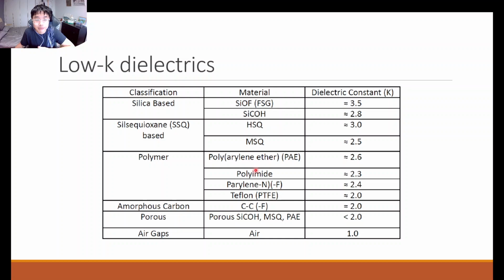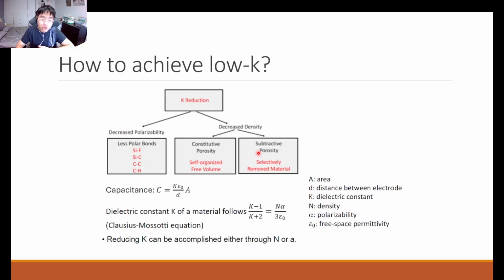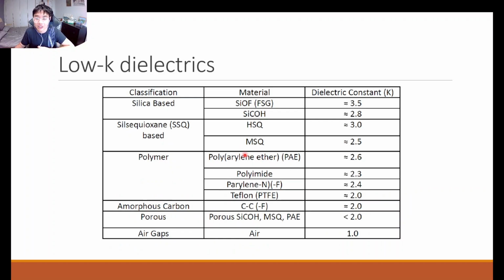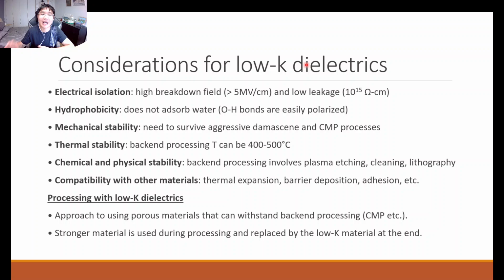There's also the idea of using polymers, because that's what I said earlier, if a polymer chain is bulky and has many bulky side groups, then you can achieve a very good constitutive porosity, and therefore a low density, low dielectric constant material, polyimide, Teflon and all that. There's also the idea of using amorphous carbon, perhaps doped with a certain amount of fluorine, and even just leaving air gaps. However, there's a problem, because if there's too many air gaps, it affects the mechanical strength, the mechanical integrity of your material.